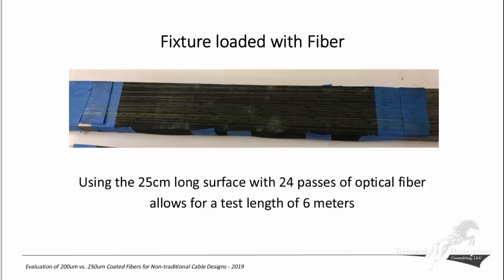Now, we loaded that with fibers, and in actuality, this is one of the most difficult portions of this whole thing, loading that much fiber onto that bar and that platen and not having any of the fibers cross each other. We used a yellow fiber so we could see it, and it's even hard in this slide to see it, but it was the best picture I could get of that.